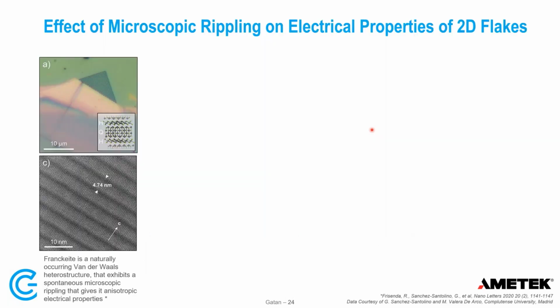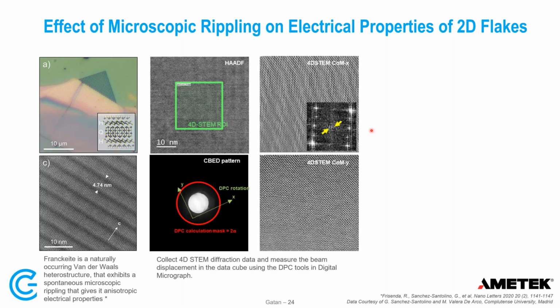Here is another example, a nice application of differential phase contrast imaging. Franckeite is a naturally occurring material that comes with microscopic rippling. The difference in the rippling and the distance between the ripples affects the electrical properties of this sample. So this customer did differential phase contrast imaging using 4D STEM to see if they could correlate the electric field to these ripples in their sample.